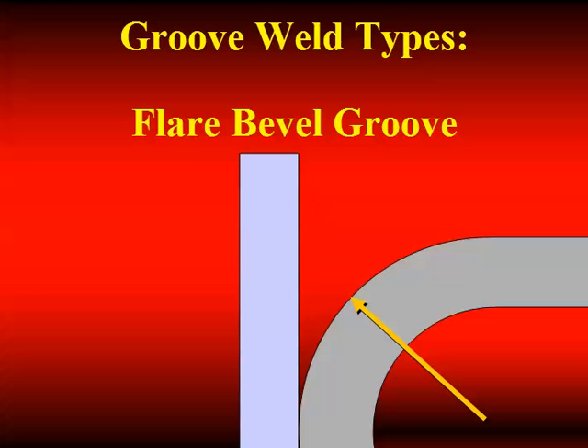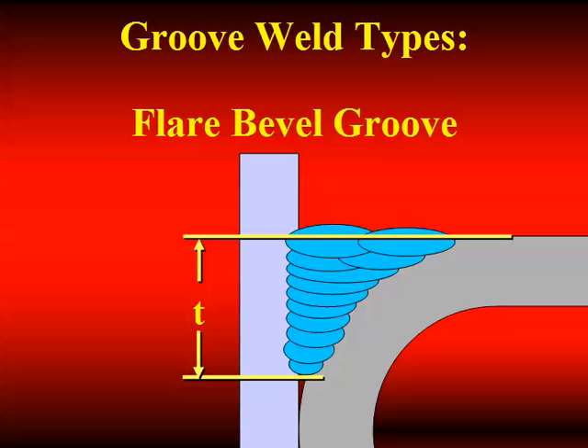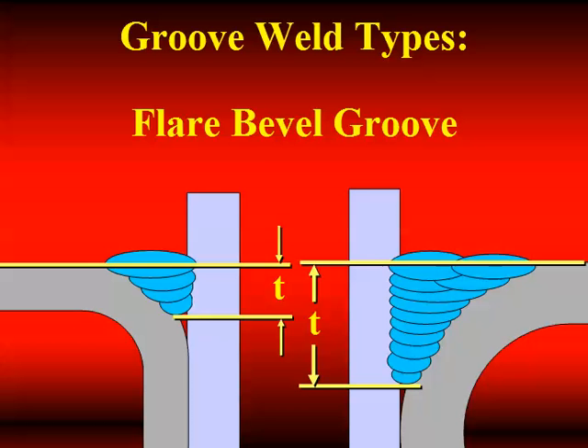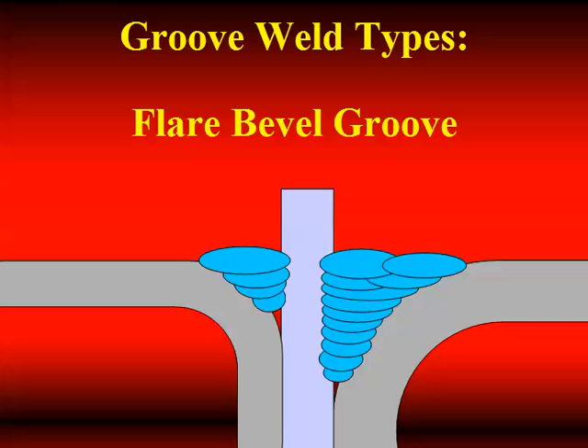And that actually presents a challenge because if we fill it flush, these result in some very, very large welds. And the more welding we get, the more distortion we get, and of course the more cost we get. And so filling flush all the time may not be necessary. Now, these are 2 illustrations of the same vertical plate thickness, different radii associated with the tubes, and the net throats that we're going to get from the 2. And I think it becomes pretty apparent, particularly if I say these are back-to-back, that you wouldn't want that kind of detail, right? You don't need that volume of welding in all cases.